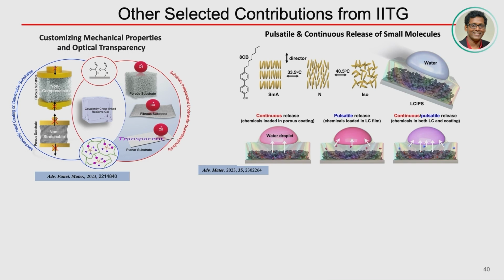And this is another work where we can release a small molecule, the drug, in two different mechanisms. One could be continuous, another could be pulsate. And this is known for a long time. The pulsate release or trigger release and the continuous release is not new. But the strategy we adopted here is that you can do the pulsate release when your stimulus is on. When your stimulus is off, your pulsate release is off. Again, you switch on the trigger, your pulsate release will be on.